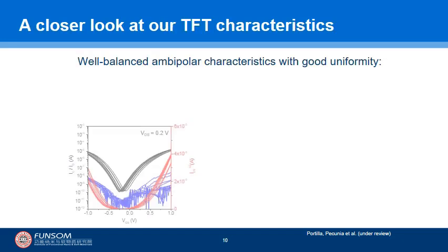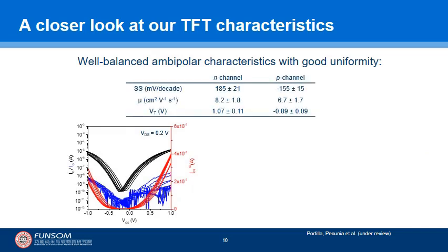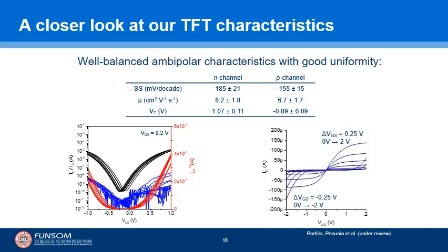The transfer characteristics of the resultant TFTs show clear, well-balanced ambipolar behavior at low voltage and with good uniformity. In fact, these transistors give balanced and comparatively steep subthreshold slopes, particularly symmetric electron and hole mobility values, and particularly symmetric threshold voltage values for both electron and hole channel conduction. The balanced capability of our TFTs to conduct electrons and holes is also confirmed by their output characteristics shown here over a voltage range of plus or minus 2 volts.